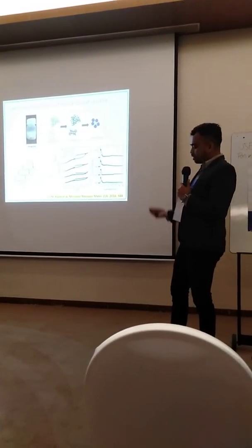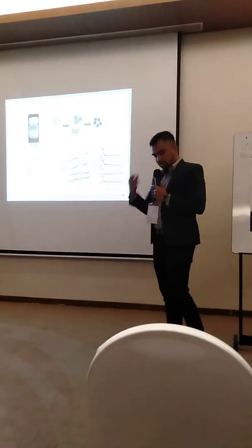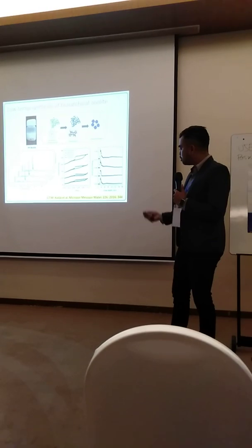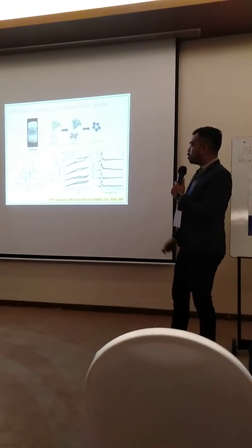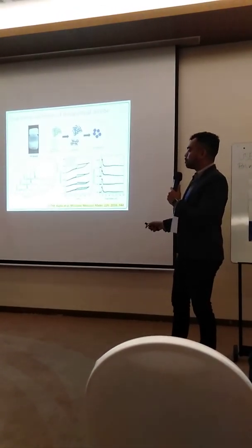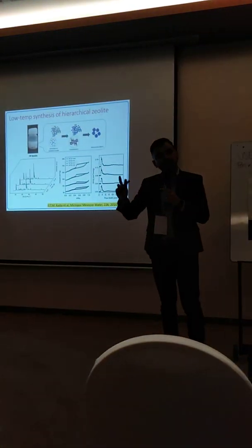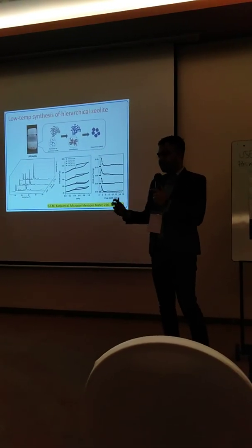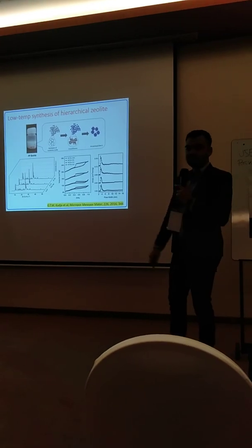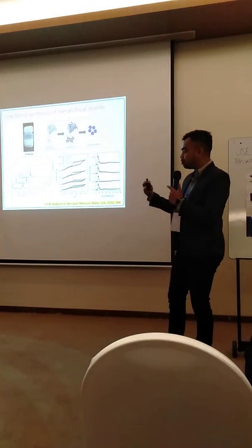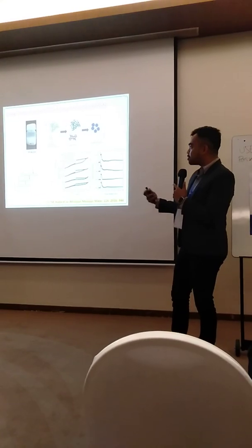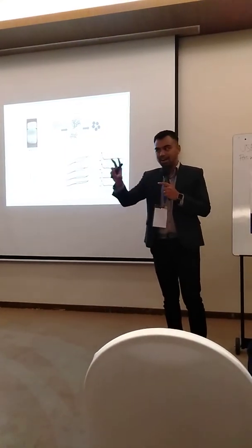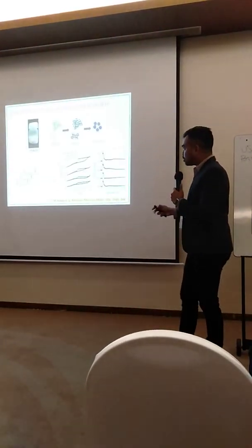So here are some of our results regarding this. We published this 3 years ago in Microporous and Mesoporous Materials. We synthesized the zeolite not in an autoclave, but we lowered the temperature below 100 degrees C. So we can conduct the experiment just in a polypropylene bottle, not in an autoclave.